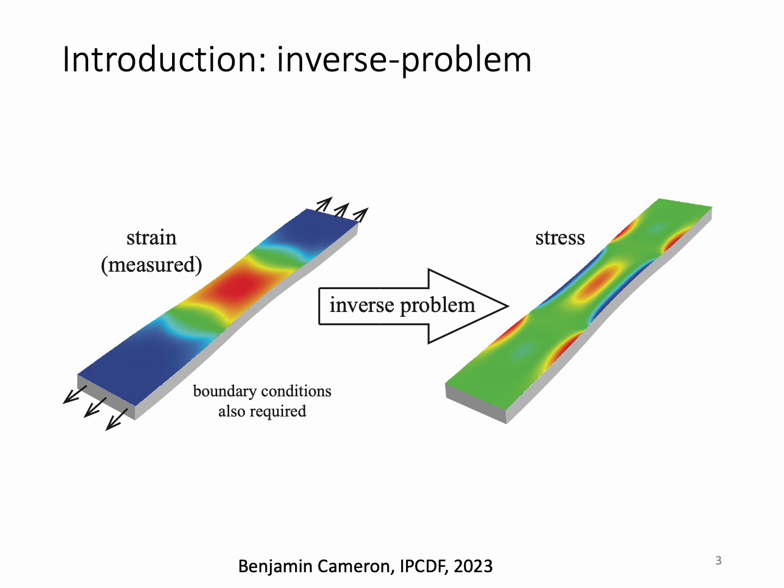The most common way of solving this is using what's called finite element model updating, which, as the name suggests, involves running a large number of simulations until the strain field approximately matches what's observed. However, in the case of heterogeneous materials, this frequently becomes computationally infeasible due to the wide range in possibilities. And for more complicated materials, even in the homogeneous case, often the strain field doesn't match within the experimental error, specifically because of the assumptions that are required to go into the constitutive model.